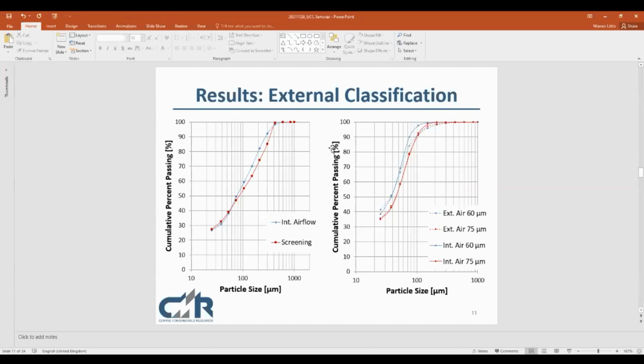So going here to the particle size distributions from the various classification tests, we have on the left the screening and internal airflow particle size distributions. This is at the coarse grind, targeting a P80 of 240 microns. We did screening tests at two different grinding pressures. Looking here at 600 kilonewton per meter squared, we get a similar P50 value, but on the coarser side we are seeing a split in the P80, with the screening particle size distribution having a coarser product.